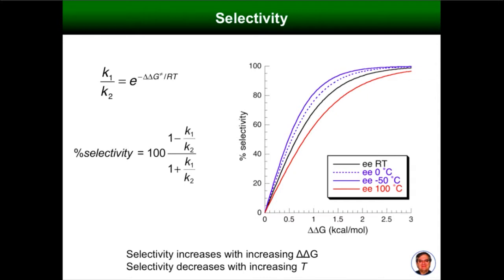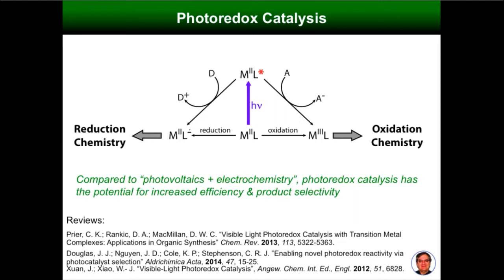And so an important attribute in thinking about what we're trying to do is how do you increase selectivity and lower the temperature for the reaction? One way of doing that, a way that we're involved with exploring, is through what's called photoredox catalysis. You take a metal complex, a dye, you excite it, you have an auxiliary agent that's either reduced or oxidized. That generates an oxidized or reduced metal complex that can then go on to do chemistry. And as we'll see, compared to photovoltaics plus electrochemistry, you can often get increased selectivity by doing photocatalysis.